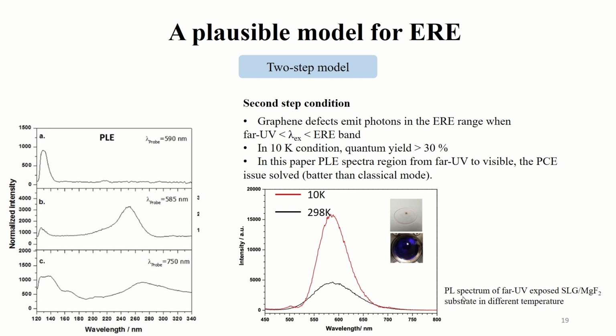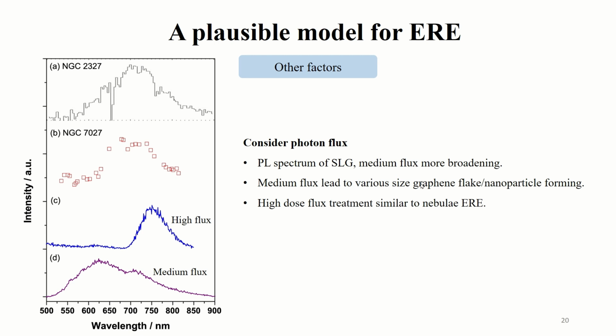In this picture, PL spectra of far UV exposed single-layer graphene on magnesium fluoride substrate in different temperatures. Red light is 10 Kelvin and black light is room temperature. The red light is bigger than room temperature. And in this paper, PLE spectra range from far UV to visible, like C part. So the PCE issue is solved, better than classical model. Classical model is photon PCE is less than 100%. And still have other factors to be considered, such as photon flux.